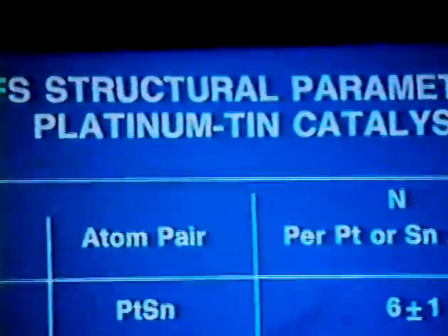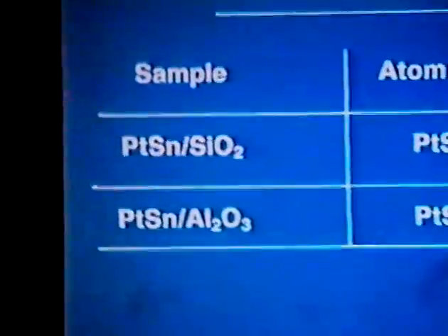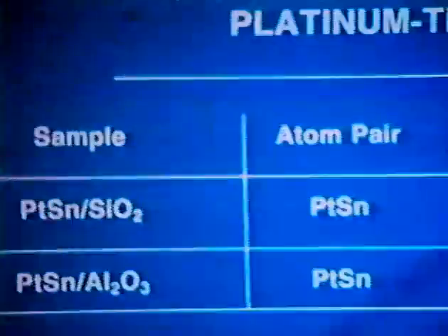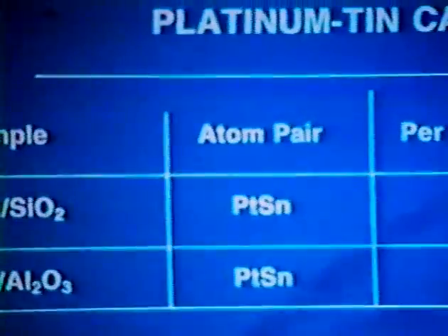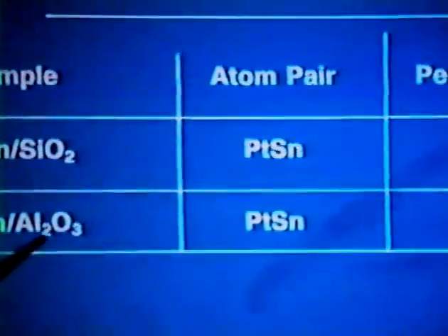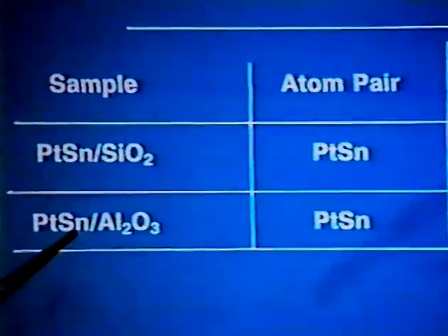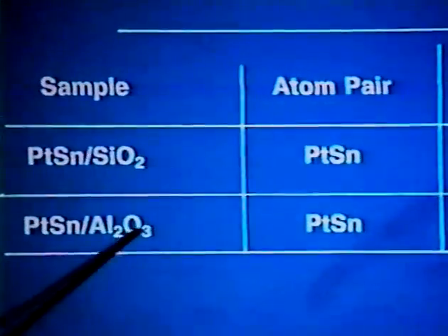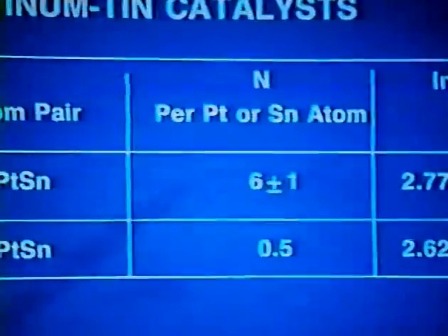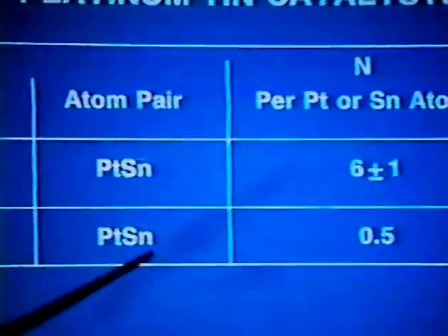Okay, platinum tin catalysts. I say EXAFS structural parameters for platinum tin catalysts. Two different types of samples. One, platinum tin on silica. This is hardly a catalyst, in fact. If you try to use it for a catalyst, it doesn't work very well. It's 1% platinum and 0.6% tin on silica. The other is this platinum tin alumina catalyst. This really is a catalyst. It's 1% platinum, 1% tin on alumina. The tin is really incorporated into the alumina matrix.